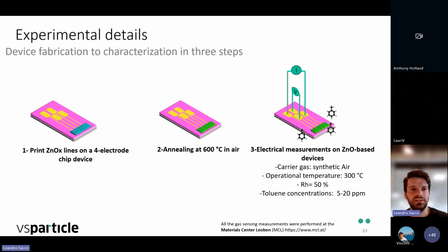So then what we did is essentially to take these lines, and we print lines in a 4 electrode configuration device. We did some annealing to be sure that we will get the zinc oxide, but if you don't want to anneal, you can also introduce oxygen in your flow during the spark, the nanoparticle generation, in order to oxidize your material. But it's also important to point out that this material is so porous that as soon as we remove it to the atmosphere, it will oxidize.